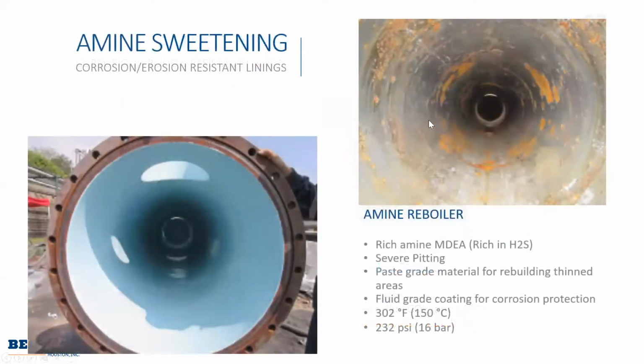So, amine reboiler. As you can see, this one has been in service, but it was done at a shop. For this one, you've got to decontaminate. You're probably going to have to desalt, clean it really well, and then pit fill it. Not much stripe coating required here. First coat, second coat, and that's your system. This one was operating at 302.